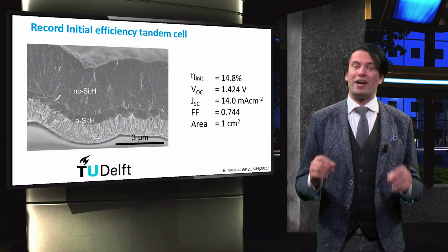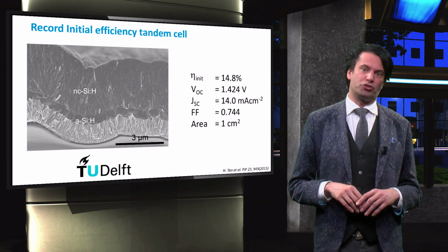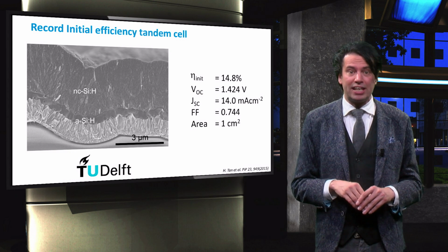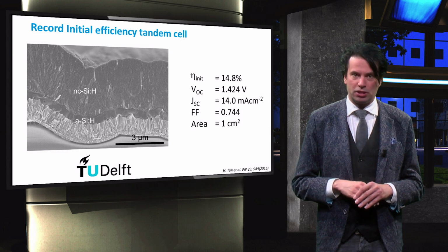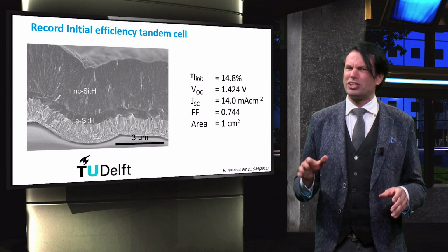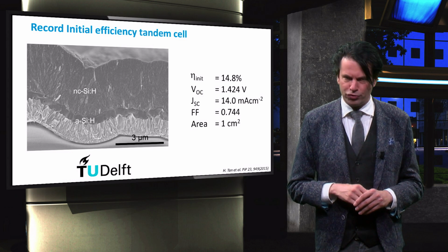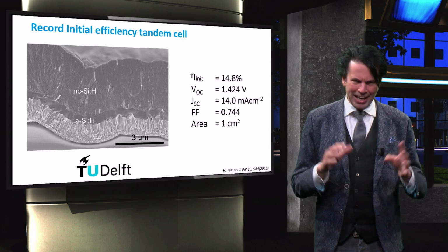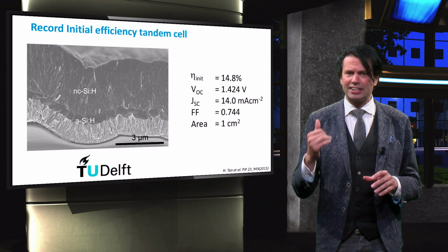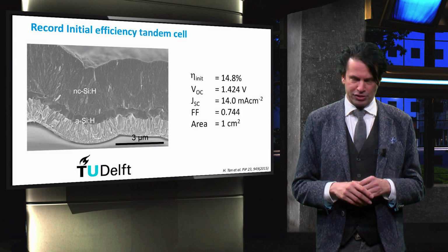This front electrode has superior conductivity combined with high transmission. This resulted in a record initial conversion efficiency of 14.8% for micromorph tandem cells. Stabilized efficiency was slightly lower than the record device of EPFL. This device concept, however, has still room to improve the stabilized efficiency further.